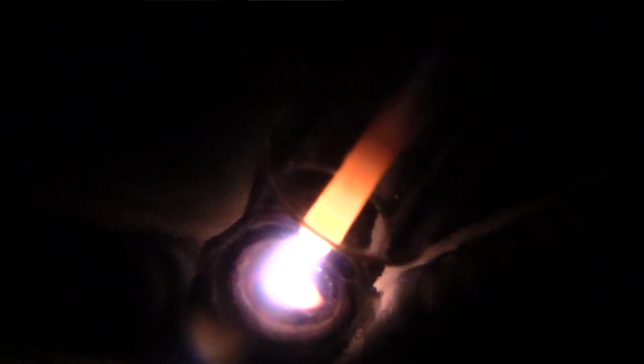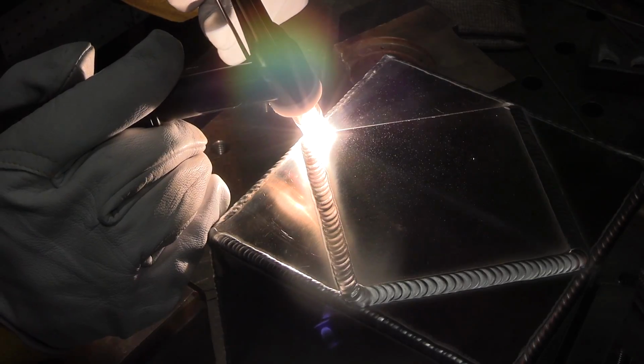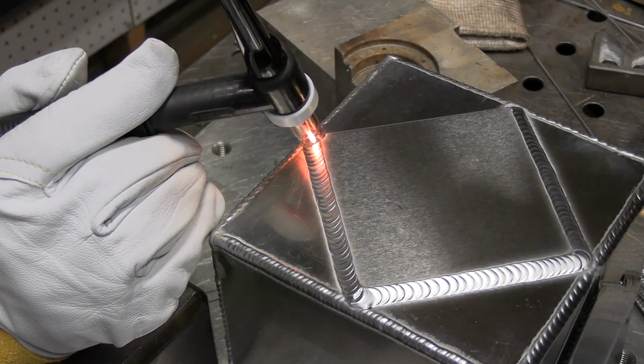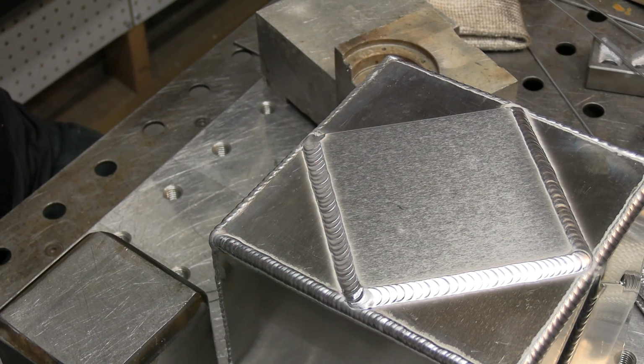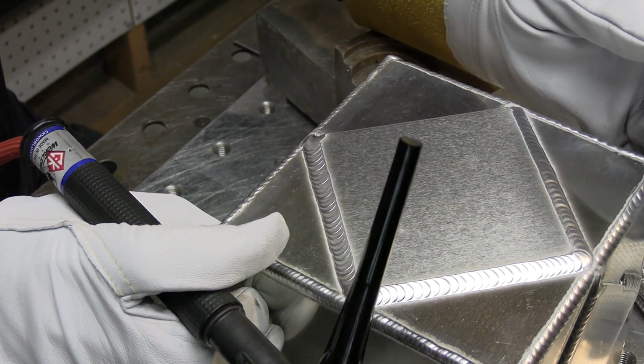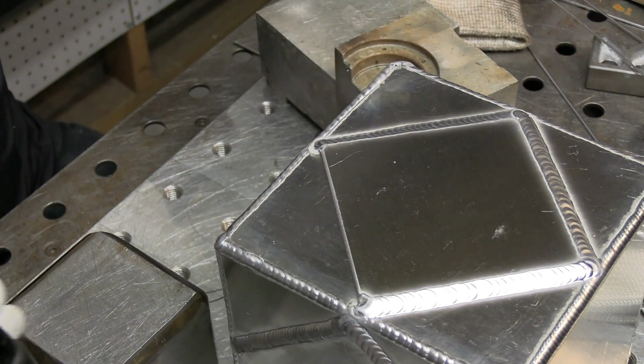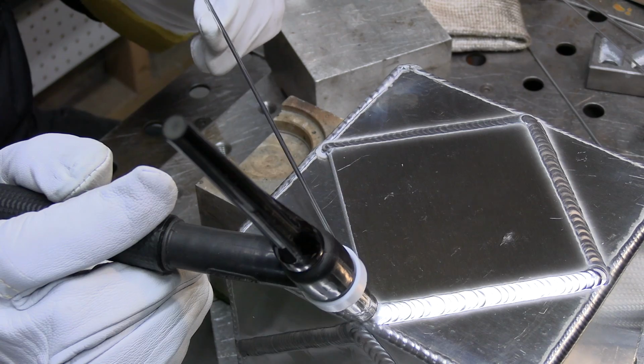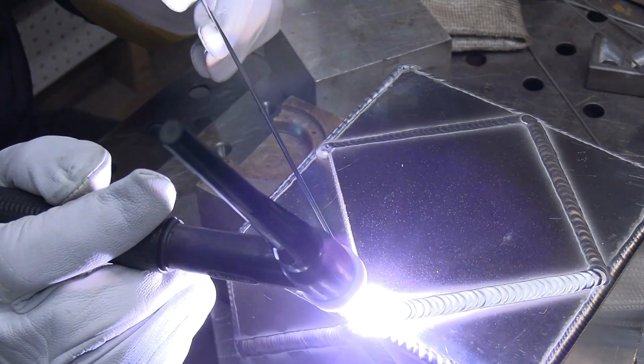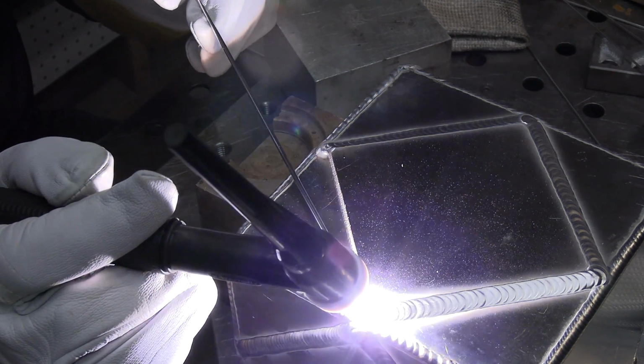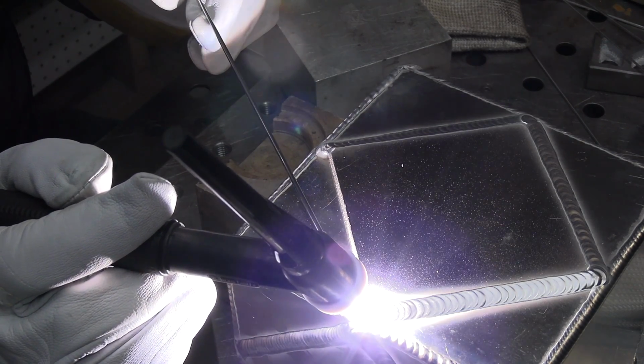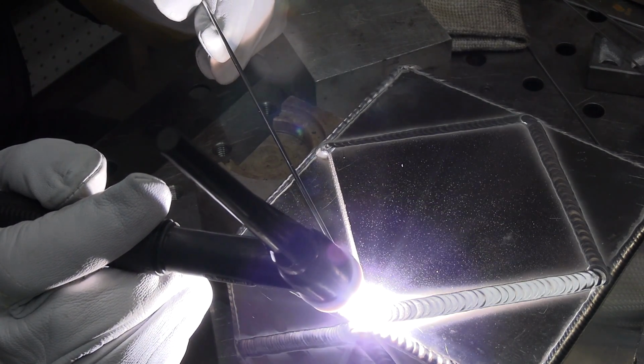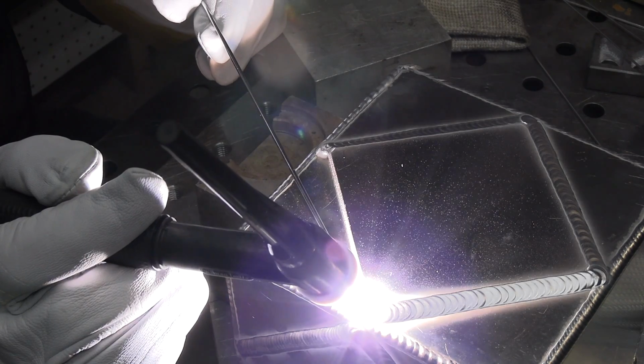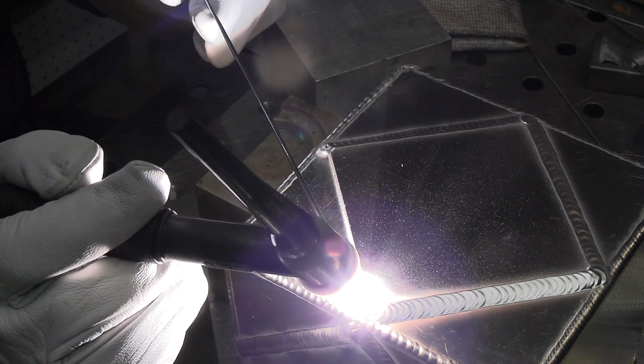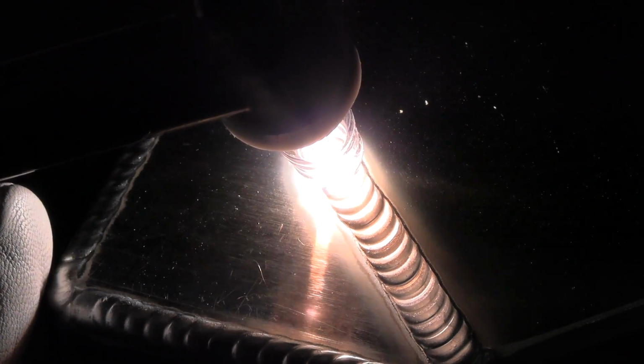Another thing on aluminum, I add a little bit of extra rod and swirl as I taper off to prevent a little crater eye, which oftentimes actually is a crack or will turn into a crack. So you don't want that. You've got to come up with a technique to prevent crater cracks on aluminum, that's for sure. A lot of times cracks initiate there and the whole part will fail eventually, all from one little star crack that started off as a crater dot. It doesn't matter how pretty your weld is if the thing fails because you left a crater and it cracked.